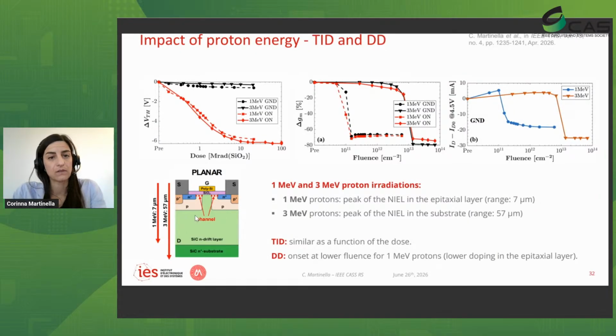One more work on that was done by comparing different proton energies. So we tested not only with 3 MeV protons, but also with 1 MeV protons. And the idea here was to try to maximize the damage in different regions of the component. So 3 MeV protons have a penetration range in the substrate, and the majority of defects are actually created at the end of the range, at this depth. With 1 MeV protons, the range of penetration is 7 micrometers, so it is within the epitaxial layer. Now we have to say that, of course, epitaxial layer and substrate have different doping density as well. We have about 10^18 in the substrate and about 10^15 in the epitaxial layer.